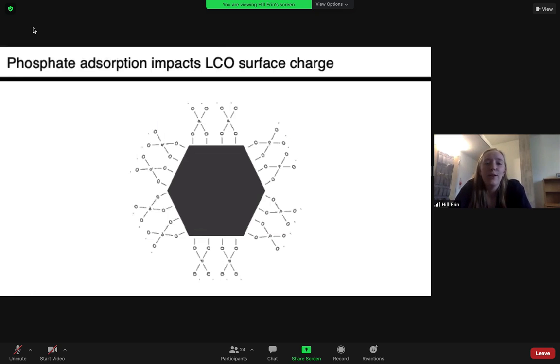So now that we know how phosphate adsorbs to LCO at the surface, we need to figure out how this impacts surface properties. My group focused mainly on the deprotonated bidentate coordination, which is one of these here. And we did that because it seemed to be the most prevalent of the three. So looking at the structure, you can see that there are two negative charges on the oxygens, and so we expect that there will be a decrease in surface charge of the LCO nanoparticles in solution when they're bonded to phosphate.